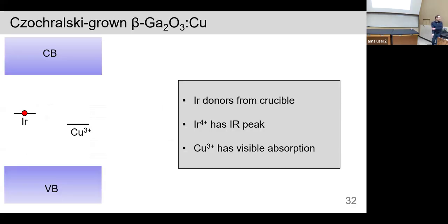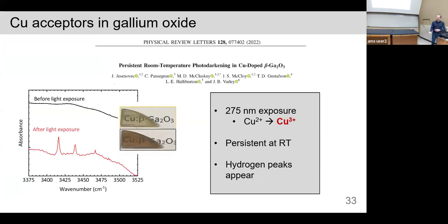Okay, so then the last example is copper doped gallium oxide. I mentioned gallium oxide already, and there's iridium from the crucible. Iridium actually has an infrared signature that we can see. And copper in the 3+ state has a visible absorption band. The 3+ state is very rare. You will not find it in nature, but it's here and there, it's been seen, and it has this broad absorption in the visible. So you can use that to tell; in the oxide, the 2+ and 1+ do not have those. So again, iridium gives an electron to copper. So when you receive your crystal, the copper is in the 2+ state, iridium is in the 4+ state. And that's just shown in this picture here. It's not exactly transparent, but it's clearer.